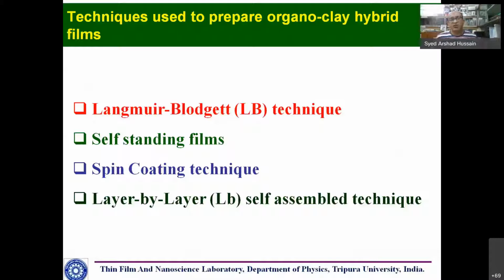Okay, so how do we prepare thin films of organo-clay systems? We use several techniques, say the Langmuir-Blodgett technique, self-standing films, the spin coating technique, and the layer by layer self assembly technique. We use these systems because these thin films are of the order of nano or a fraction of a micrometer, so you need sophisticated equipment to do these things. These are the standard techniques we use.